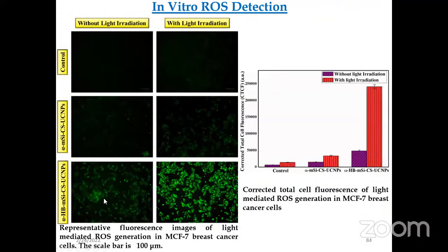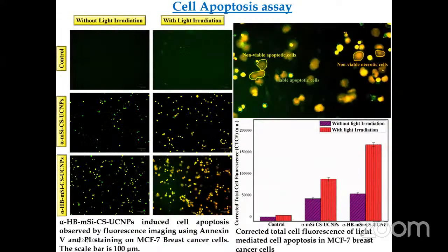You can see that we exposed the material to the MCF cell line, where in the presence of a light source, more ROS was generated. The fluorescent image clearly indicates more ROS generation with light irradiation. That is directly correlated with the apoptotic or anti-angiogenic effect of these systems. We also did an apoptosis assay, where we showed fluorescent cell-induced apoptosis using Annexin V and PI staining. We could show cell death, non-viable apoptotic cells, which we can see over here.